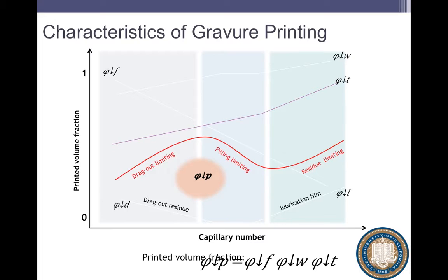We want to be as high up on that curve as we can. That would indicate we're printing what we want to print. When you go really slow, you don't print very well, and the reason is your wiping is dragging ink out of the cells. If you go faster still, you're also not printing really well, because now you're trapping air inside the cells. If you go really fast, you think things are good, but there's also a residue that gets deposited where you don't want it.